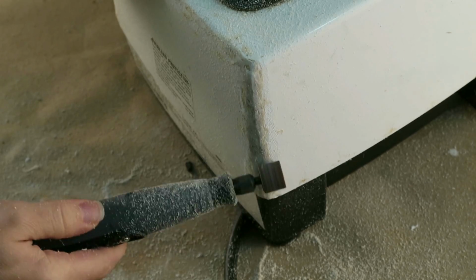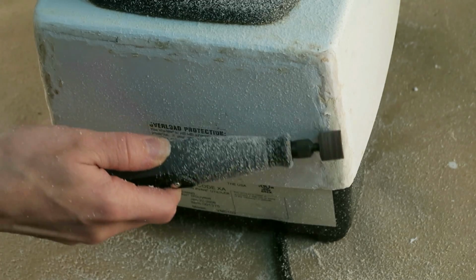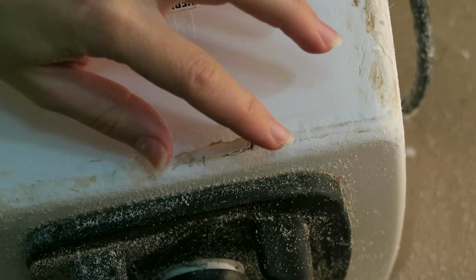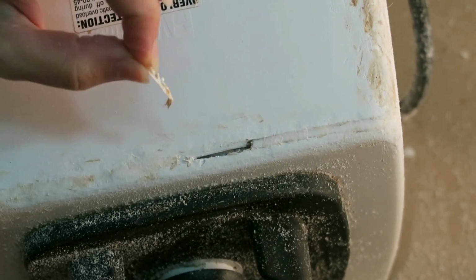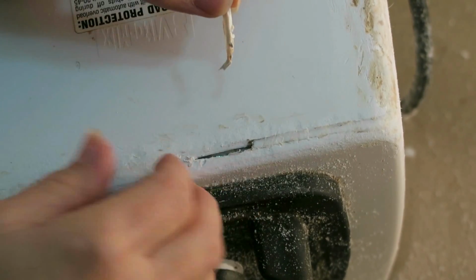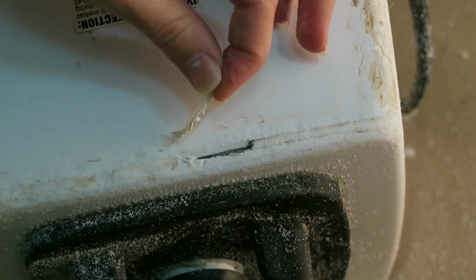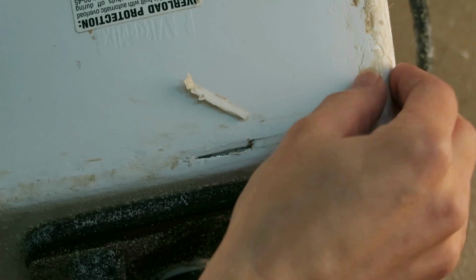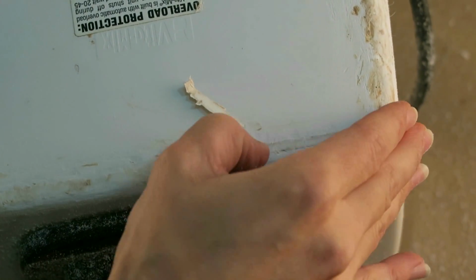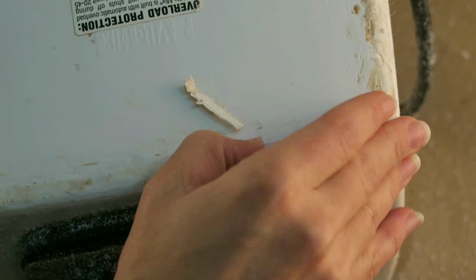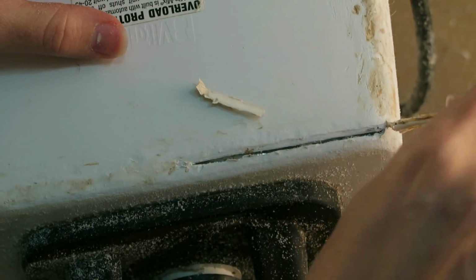I thought I was done welding, but as I'm sanding away the excess plastic, I can see how uneven the thickness of the weld is and how poorly adhered it is to the area where the temperature was lowest and the parent plastic was not melded with the filler. This shows that it is truly important to melt and mix the parent and weld plastics together.